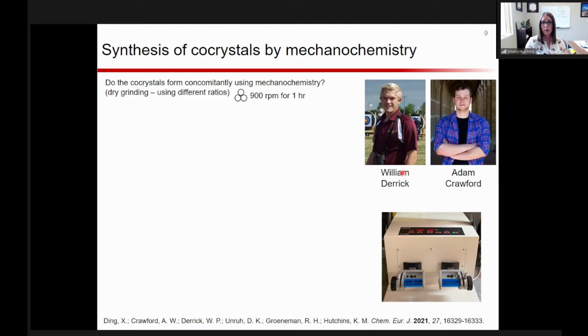And my undergraduate William came on to help at this point as well. And so what we decided to do was actually do milling, and we did not add any additional solvent, so just dry milling. And we're using a speed of 900 RPM for a period of an hour, again with our FTS mill. And we chose 900 simply because it's in the middle of the instrument, and it was sort of new for us at the time, so it's sort of middle capability.